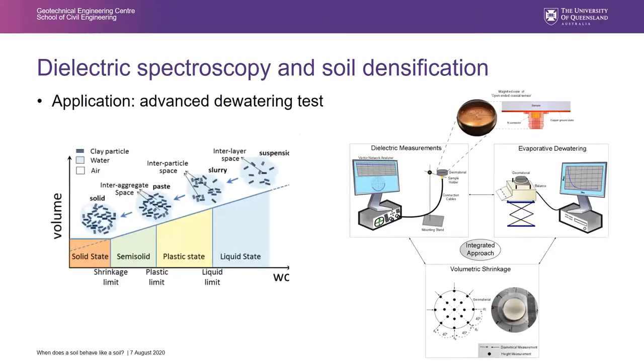And then we've been working a lot on this dewatering method. Like Alex showed, it's very important to be able to understand the different states of the soil. In this test, we made a classic dewatering test by the loss of mass and computed the evolution of volumetric properties. And at the same time, we measured the dielectric properties.